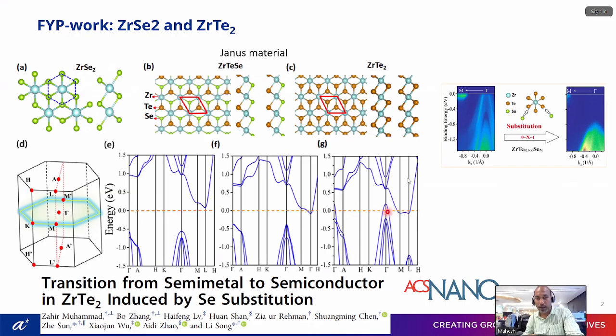Here you can find the inverse band gap, so the band gap is negative, kind of. So this is a very good dopant to tune the electrical properties. But I found that when we dope more tellurium-rich, these compounds are not stable. Even 2D materials like MoTe2 and WTe2 are not stable. In bulk form also, after a few days everything bulges out and absorbs moisture. So tellurium-rich is not as stable as selenium. While handling the material, I keep it in the glove box later.